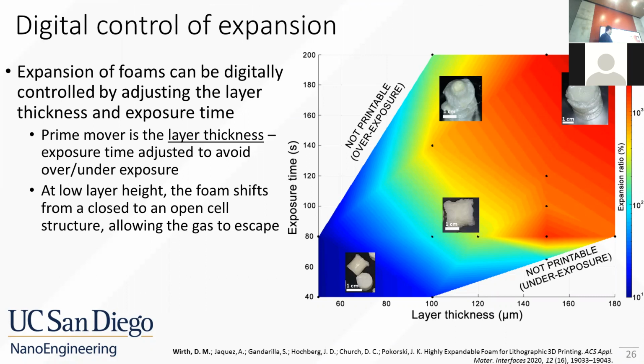This is a contour plot of exposure time and layer thickness, where the color goes from blue to red, blue being basically 0% expansion, and red being 4,000% expansion. If you go outside of this contour plot, you end up with structures that are not printable, either overexposed or underexposed.